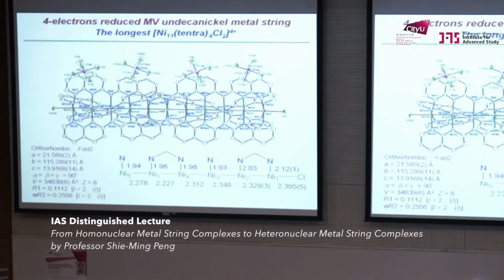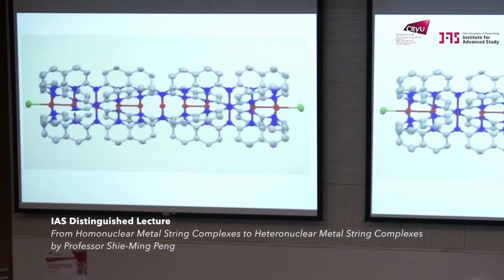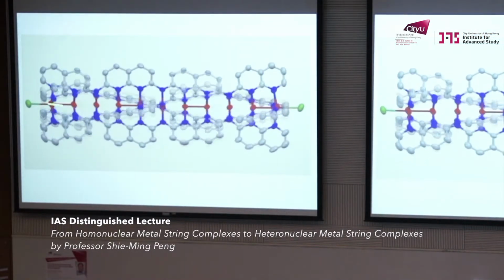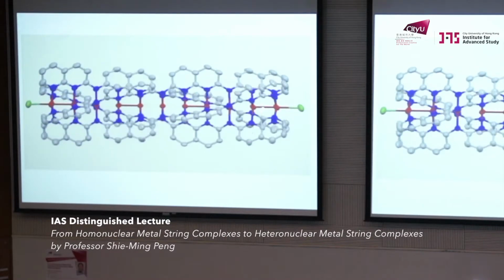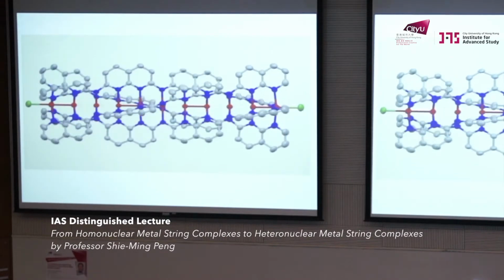And we have the crystal structure of this 11 nickel. And the hook represents the naphthyridyl unit. So it's symmetrical, so I only show you the 4 nickel. Okay. Once you have the nickel 1, nickel 2 mixed valence unit, the nickel-nitrogen distance becomes longer, and the nickel-nickel distance becomes shorter. So this is the bond model of this metal string. When you have mixed valence units, actually you have a partial sigma bond.